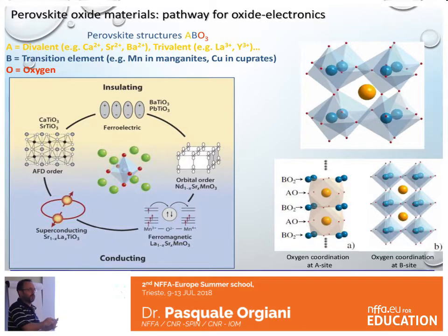Why is it so important with the perovskite, this way of controlling the structural deformation? Because in most cases, the physics of the perovskite is driven by d orbitals, which are known to be highly anisotropic. This means that if you change the distance a little bit, or the angle between the atoms a little bit, you are changing the overlap of the orbitals in a very, very strong way. Then you can turn from an insulator to a metal, just by changing this small angle, this small arrangement. Okay?